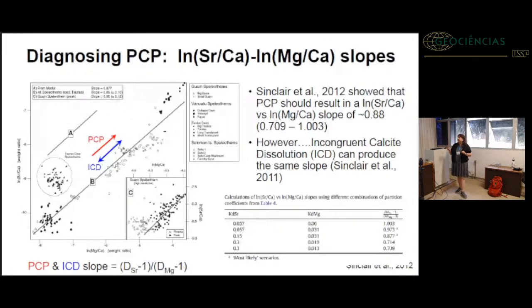PCP should result in a linear slope in log-log space of strontium calcium versus magnesium calcium with a slope of around 0.88. And the reason for this, they prove mathematically, is that this slope should equal the D strontium minus 1 divided by the D magnesium minus 1, okay? So you can plot magnesium calcium and strontium calcium against each other, either for your drip water data or for the calcite data, and see that there is a correlation of 0.88, boom, PCP, you can interpret your data.